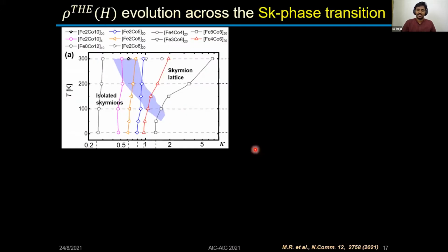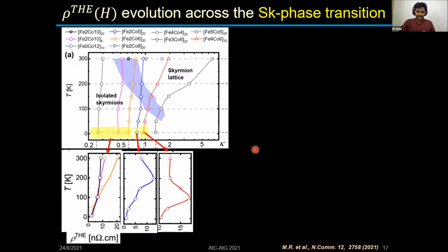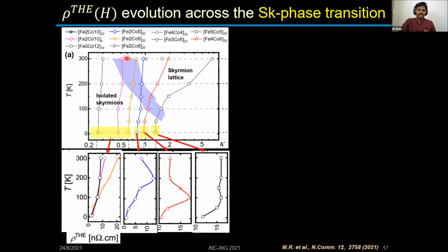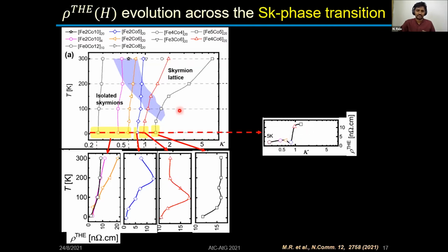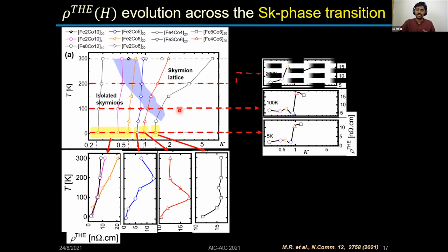So what we did is then to track the magnitude of the topological Hall effect across this phase diagram as we go from isolated phase to lattice phase. What we see here, either you move along the temperature, strictly in this case, we are not fixing the kappa vertical line, but largely if you change the temperature, which is also changing kappa in this case, we see a local maximum emerging in the topological Hall magnitude whenever we are around that transition region. And that is also true if we fix the temperature and sweep the...